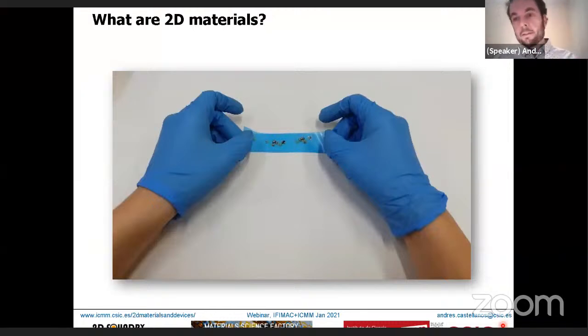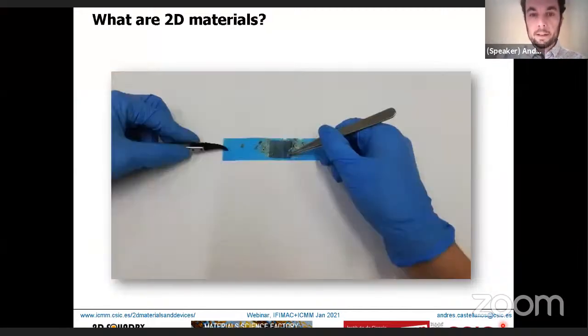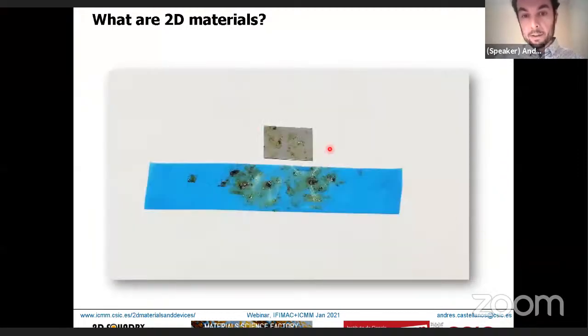So now you believe that with the Scotch tape you can cleave these crystals and thin them down. The next thing we do, in order to transfer these crystals that are living on the surface of the Scotch tape, or the adhesive tape, to a substrate, is we place our acceptor substrate in contact with the tape, and we peel off gently, and what you get is the transferred flakes on the surface of your acceptor substrate, like this one here.